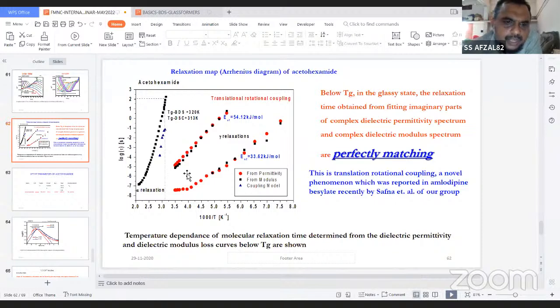That is, I told you, there are two types of relaxation. One is a primary relaxation above the glass transition temperature. That is, this is the primary relaxation, that is alpha relaxation. This is the secondary relaxation, because since I am plotting in the reciprocal of temperature, the higher values correspond to the low temperatures. So this right side of this dot represents the glassy state.